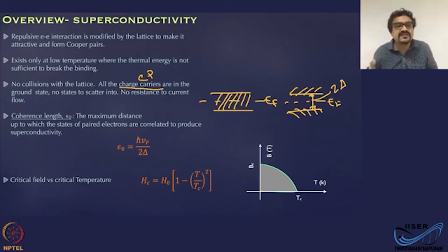What that means is, as long as the applied voltage is not sufficient to break this Cooper pair, the energy that the Cooper pairs are gaining is not sufficient to break it into individual electrons. These Cooper pairs cannot scatter, so there is no resistance to the flow of current, because the resistance comes from scattering. It's one single state, one single wave function, which extends from one end to the other end of the sample, and that lies at the Fermi energy. So if the applied voltage to run the current through the system is small, less than the energy gap, then there will not be any resistance to the flow of current, which is the origin of zero resistance or superconductivity.